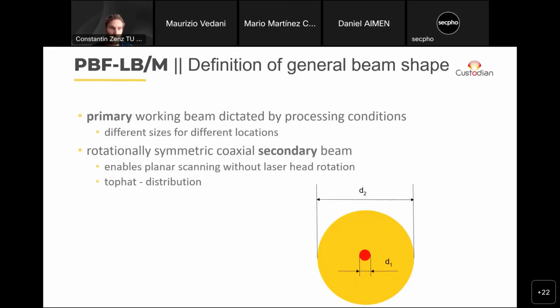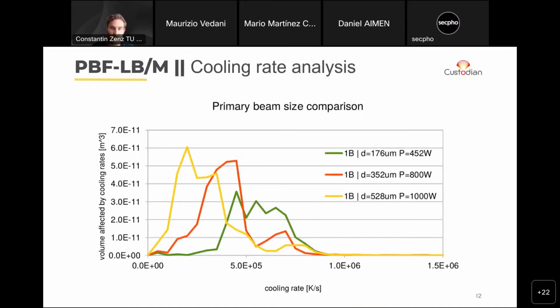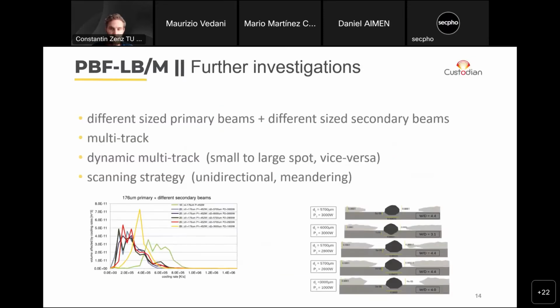As we already saw before, the beam shape that was agreed upon was one primary beam with a Gaussian power distribution, and then a secondary beam, which is a larger circle with a top hat distribution, with the aim of providing some additional heating to lower the cooling rates and therefore reduce the cracking risk. So this is just a little larger the plot we've already seen before, comparing different primary beams.